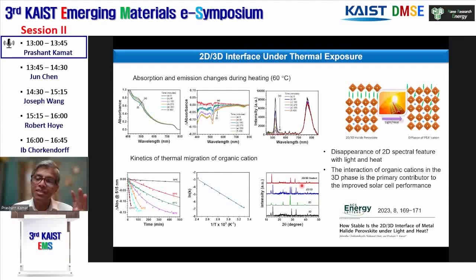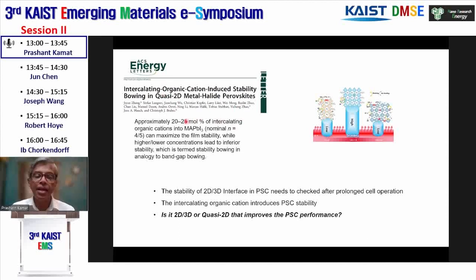Recently, there was a study where they deliberately added organic cations, so they can do these studies, and they showed that the stability of the 2D interface needs to be checked after prolonged cell operation. For PSC stability, it is not the 2D layer, it is the intercalating cations that are making the difference. So now the question is, is it 2D, 3D, or quasi-2D that improves the PSC performance? This is something to think about.